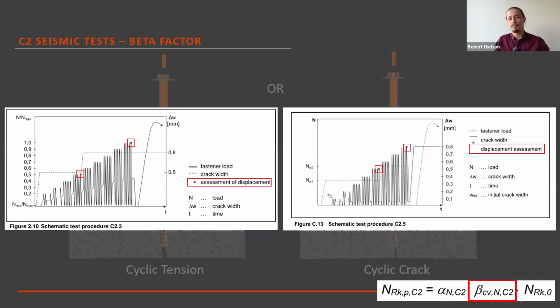Just quickly on the beta factor, what this is doing is accounting for displacement performance of anchors. It doesn't, in my experience, really have a big impact on the end result in terms of the capacity. Might have a little bit, but not a big reduction. But what it does do is it has pass-fail requirements. The two things it cares about basically are the spread of displacements across multiple tests, and so what you're protecting against there is unpredictable displacement performance of anchors, which is not something we want. And it also has a maximum displacement of 7 mm in the test.